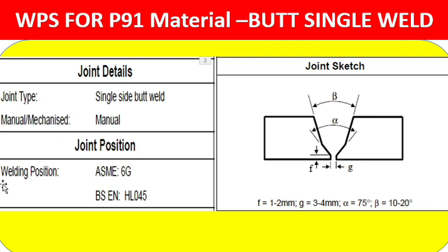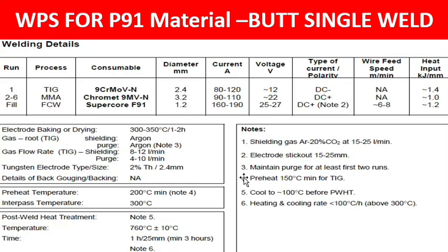Now you can see here the welding details. 1 is TIG, 2 to 6 is MMAW, and fill is FCAW. So three processes here. One is TIG. The first run will be TIG welding, with a 2.4 mm diameter electrode. 80 to 120 amperes current is required, with DC negative. You can see here because root is required, that is DC negative.